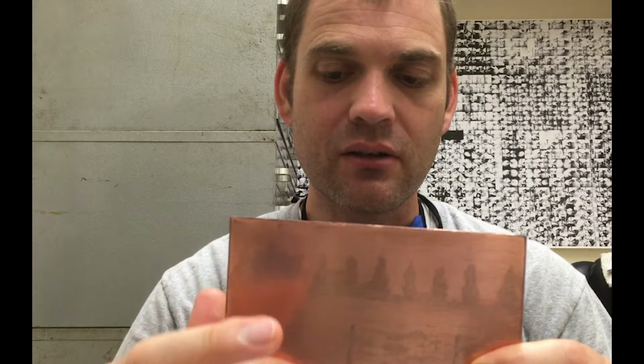I stopped out the lines that are at the top after about 10 minutes and progressively worked down, till the lines at the bottom had well over an hour and a half of etch time. The longer a line is exposed to the etch, the deeper the bite gets and the more ink the line will catch. So if you want to have variable lines, you have to learn to work with stop out and multiple dips into the etch tank.